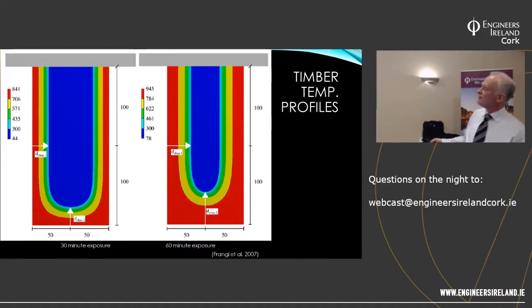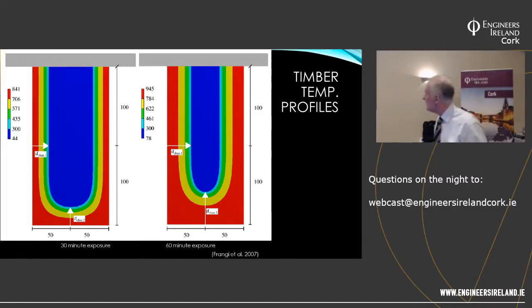Now, temperature profiles. So the kind of mid blue in the middle is 300 degrees down. So at 30 minutes, this is a 100 millimeter wide by 200 millimeter deep beam, so a normal enough beam. At 30 minutes, in the middle here, it's still 44 degrees centigrade. So if that was in a kiln, it'd be about 838 degrees on the outside. Yeah, 841. So it's 841 on the outside, the kiln itself. And this is charred around here, but it's still 44 in the middle. It's a very good insulator, timber. That's why it's retained the strength very well if the fire will put itself out or be put out.